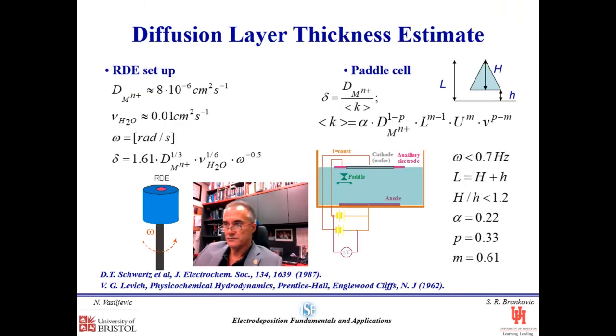The determination of the thickness of the diffusion boundary layer is somewhat different across the different geometries of the electrodes, but I give you here two examples which are most commonly used in the literature. One is defined by Levich for the rotating disk electrode, where the diffusion layer thickness is a function of the kinematic viscosity of the water, rotation rate, and diffusivity of the metal ions in the solution.